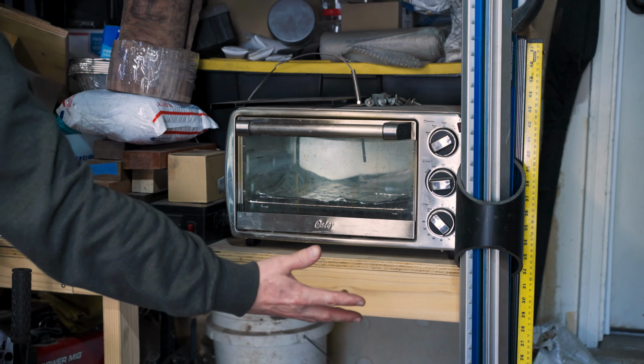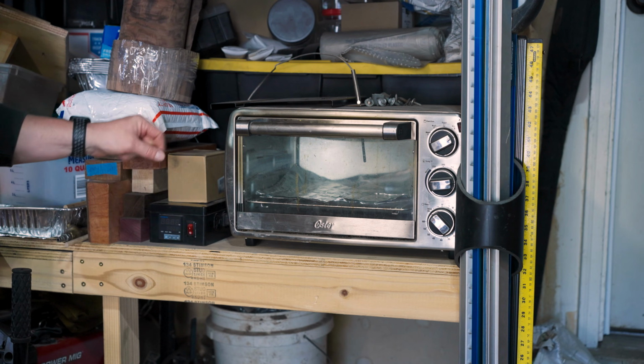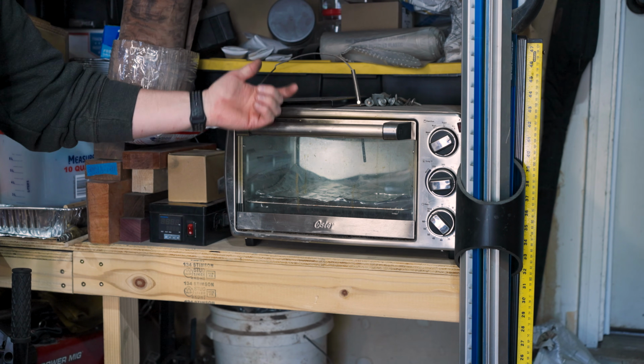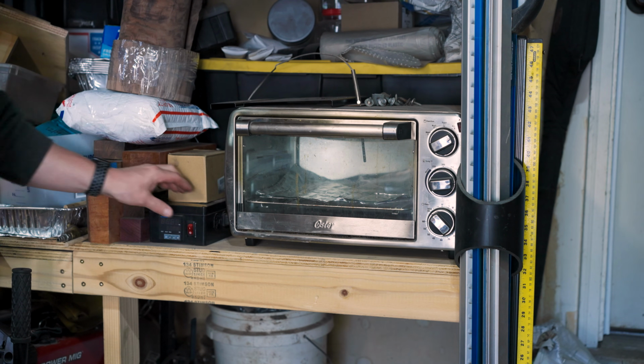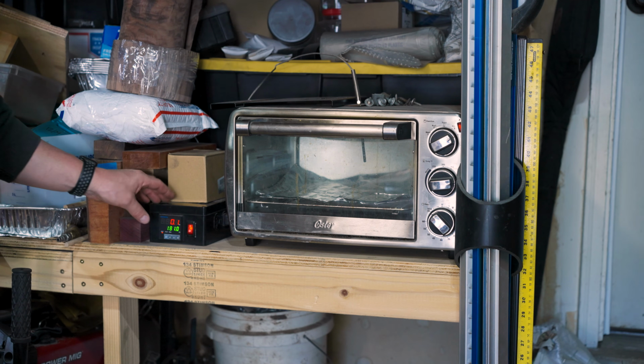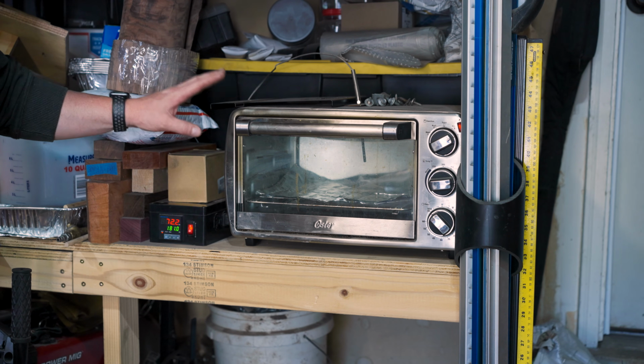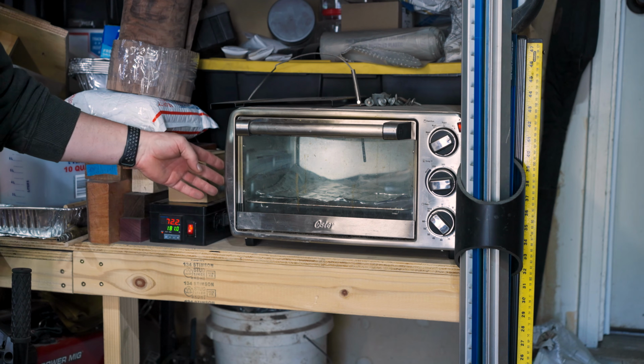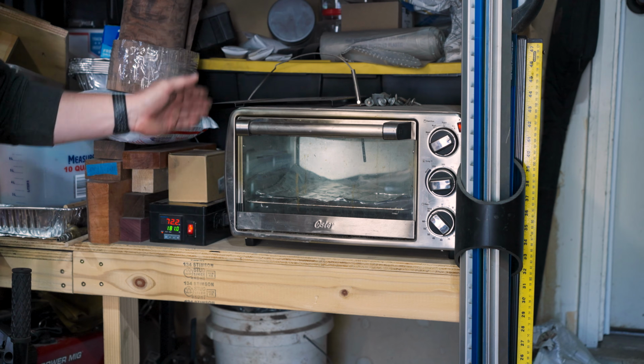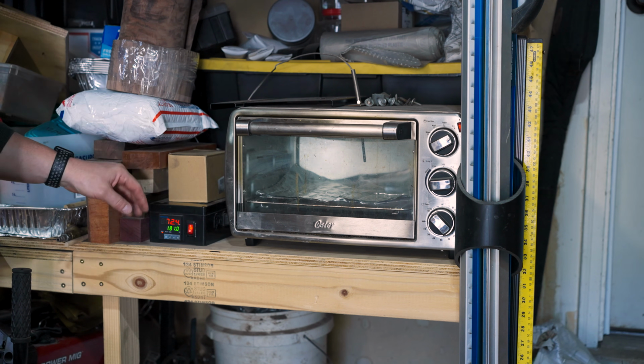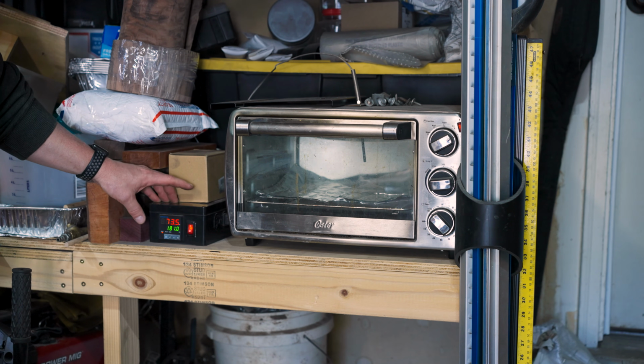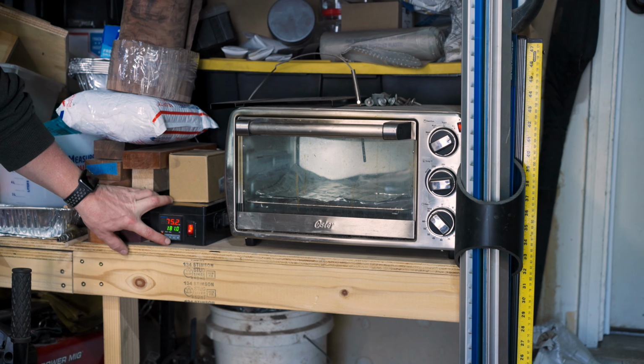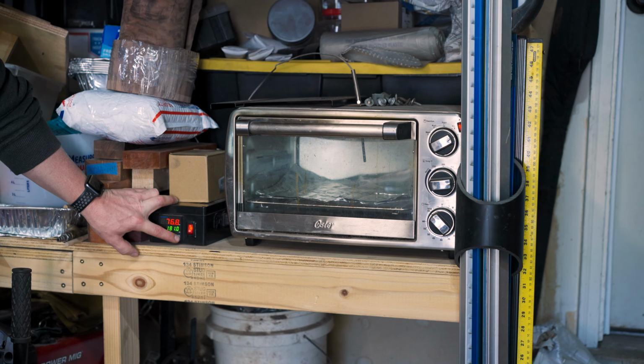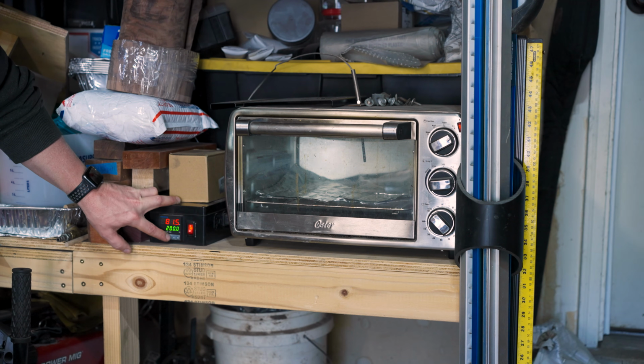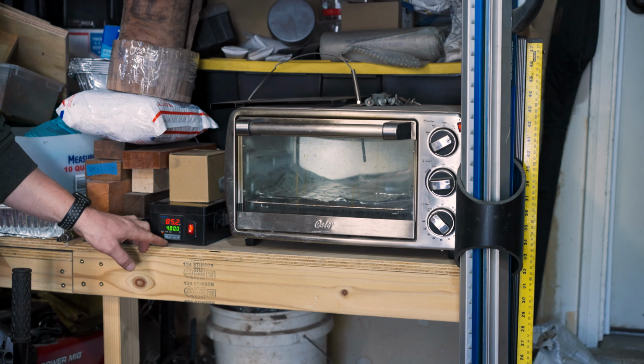So here we are at the tempering area. Depending on how many knives I have, I will sometimes use the kiln to temper, but because I've only got one knife, I'm just going to use this toaster oven, and toaster ovens are notoriously inaccurate. So what I've done is I've taken this one and insulated it just a little bit so it holds heat a little bit better. I mean, the glass door doesn't help, but it holds heat better. And then I've made this temperature controlled PID, which I use for a lot of different things. But I'm going to temper this at 400 degrees. Just like that. So we'll set that at 400, keeps the temperature.